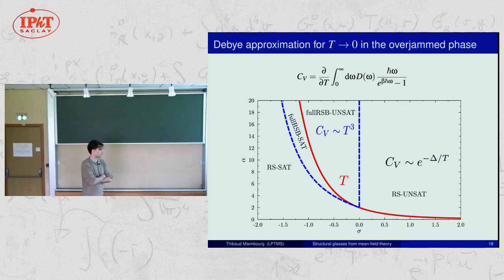Yeah, of course. And can you get that, or is it beyond this? No, it's okay. So this is within Debye. Within Debye, you expand the potential, so the density of states doesn't change. But what we show here is that, with the fact that the specific heat changes, this means that the fully quantum density of states is different from the vibrational one, and that we get a mismatch between the two.